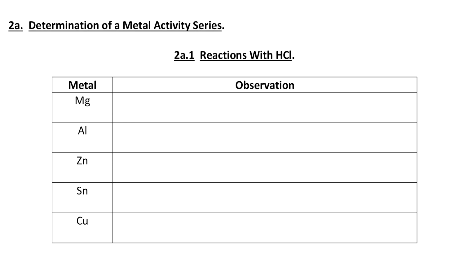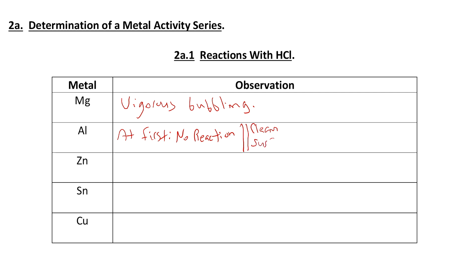So now let us look at the full set of experimental results for the data tables in this experiment. So in procedure 2A1, reactions with HCl, we found with magnesium vigorous release of bubbles, vigorous bubbling, let's say. With aluminum at first, we observed really nothing, no reaction. Later on, after I did the video, I took a piece of aluminum and I cleaned off the surface very well with steel wool, and after doing that, when I put that piece in hydrochloric acid, 1 molar hydrochloric acid, there was also a vigorous reaction.